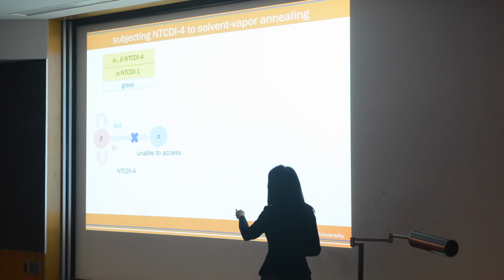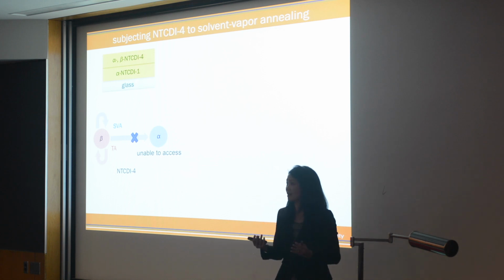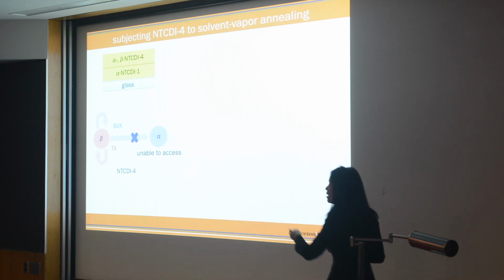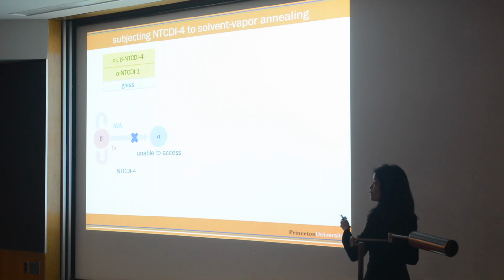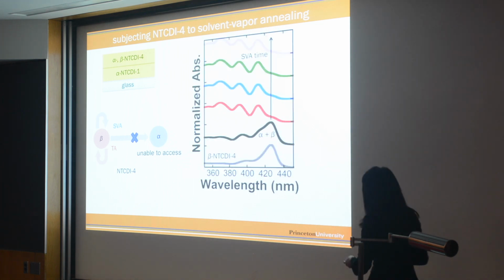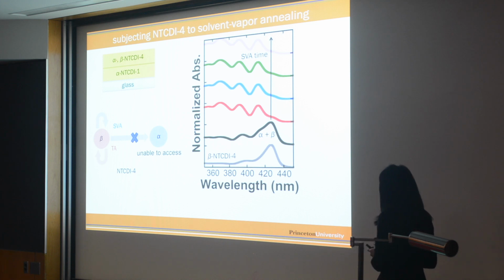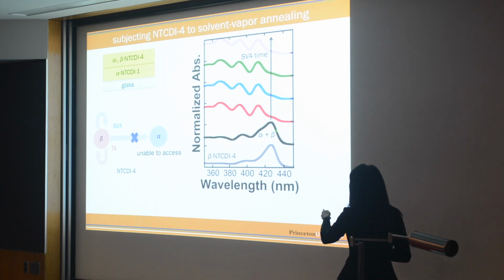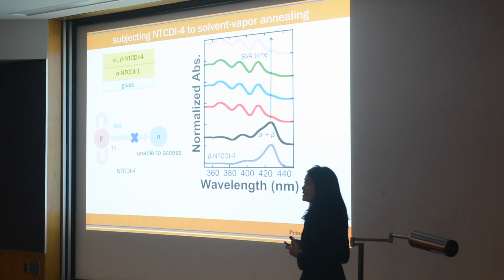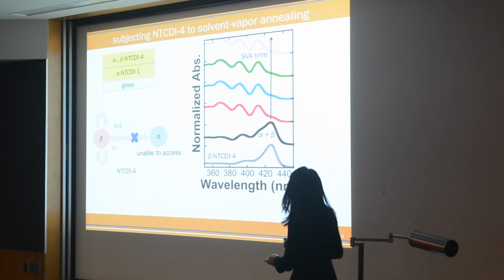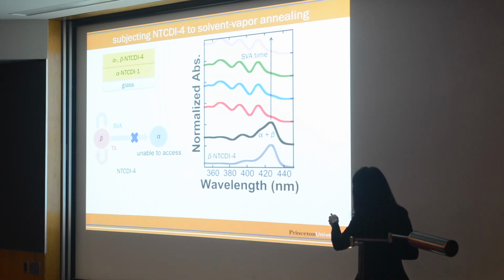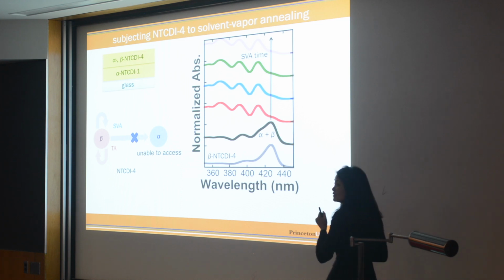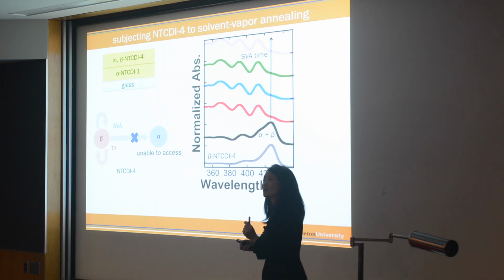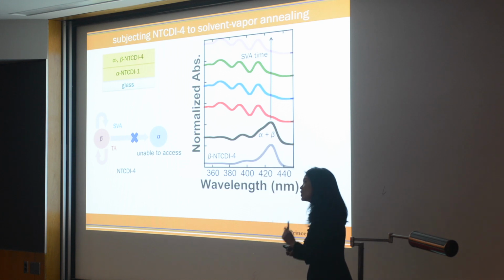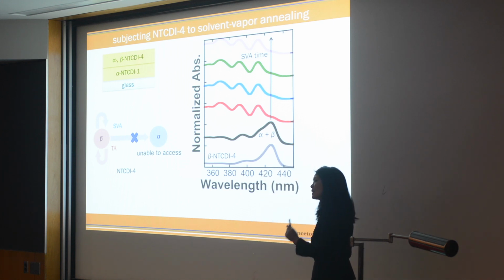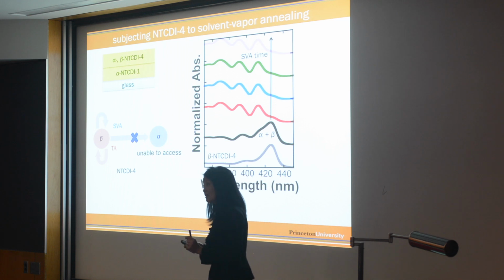So then the question is, well, now that we have alpha and beta NTCDI4, can we now do this transformation, right? Previously, when we only had beta, we can't access the alpha. Now, in the presence of some alpha, can we access alpha with the rest of the beta? And so this is the data. This is just a reference, beta NTCDI4. This is what we start out with. We have alpha and beta NTCDI4. And as we solvent vapor anneal, true to form, the beta actually slowly converts into the alpha phase. Now, this data is significant because it's telling us that previously when we could not access alpha, it's because the barrier is a nucleation barrier.